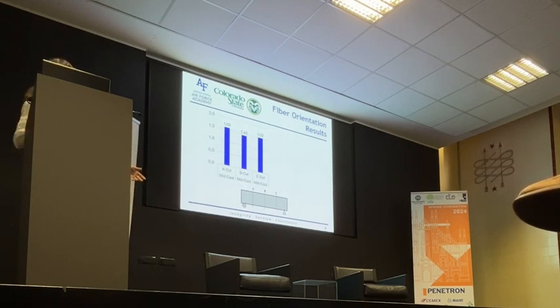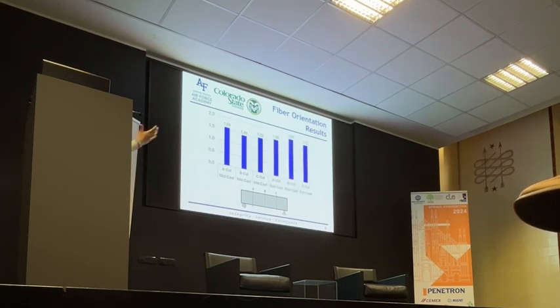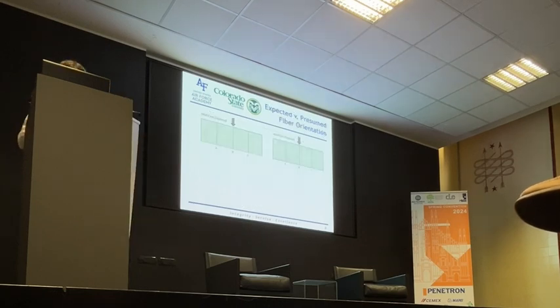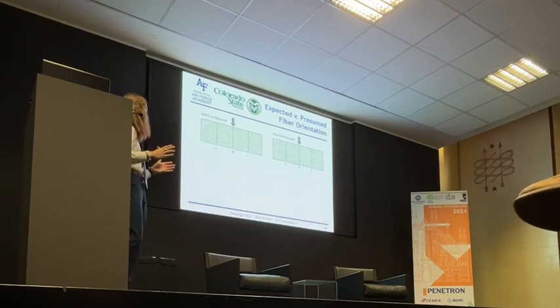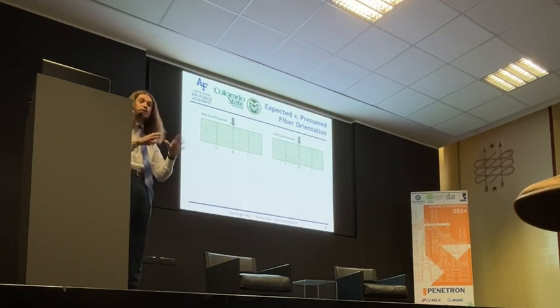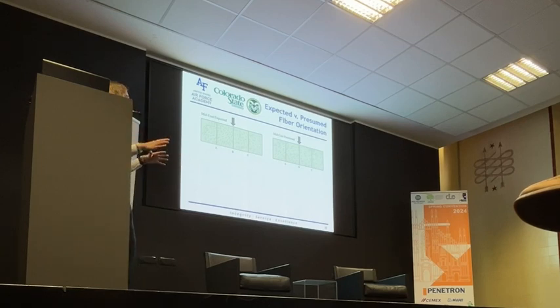So what happened when we poured from the ends? Well, exactly the opposite, which would make sense. Where we poured at A and C, we found that those fibers were more perpendicular to that cross section than at B. And that is the opposite of what we expected. Previous research had shown that fiber orientation had to do with flow of the UHPC, but based on that image analysis with the aspect ratio, we found the opposite.